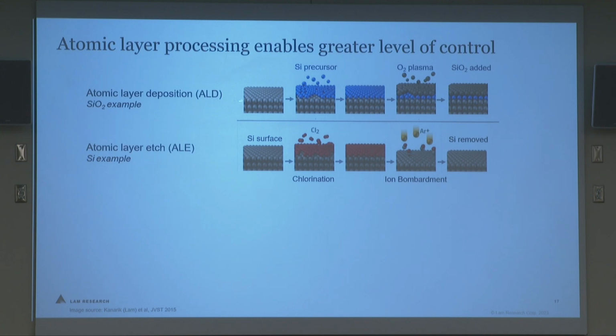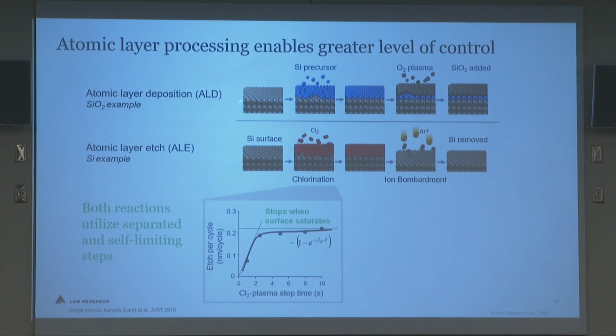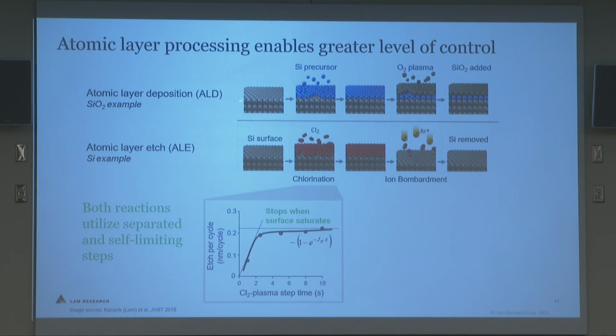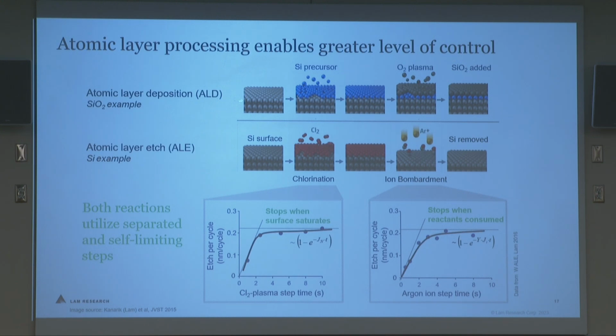If it's too much, you just start etching continuously, and you've got reactive ion etch again. But if it's not enough, then you don't remove that layer. So the key is that they are separate steps, and they're self-limiting. So this is an example of the chlorine exposure time on the x-axis and the etch rate per cycle on the y. You can keep exposing more chlorine for longer, but you're not going to remove any more film because it will saturate. And the same with the next step.